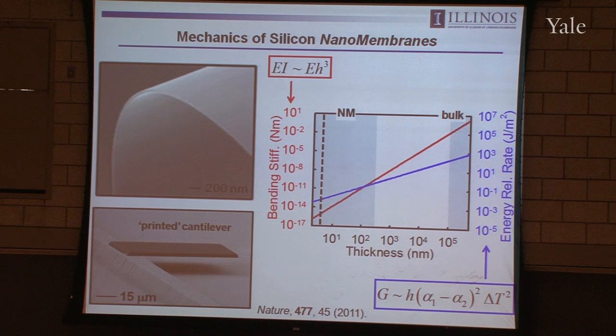And that cubic dependence of the bending stiffness on thickness really provides a powerful lever for creating a flexible form of silicon from something that you typically think about as an intrinsically brittle material. So in fact, if you go from a wafer scale thickness of silicon, you have a bending stiffness that's about 10 Newton meters. If you decrease the thickness into this nanomembrane regime, you can go from 10 Newton meters in bending stiffness down to about 10 femtonewton meters. And that has a qualitative impact on the mechanical characteristics of the material. You go from a plate of glass to a floppy noodle, essentially, just by reducing the thickness.